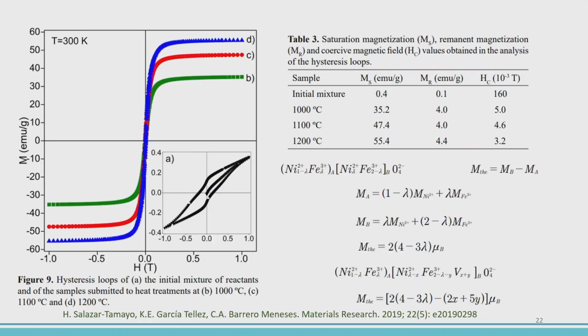And finally, I want to show this, my hysteresis loops of the initial reactants and for the 3 different temperatures. We just want to concentrate on the saturation magnetization, and you notice that as the temperature increases, the magnetization increases. How to explain this? I saw earlier work yesterday that perhaps there is a canting, and with this formula we are not assuming canting, we are assuming that this is a collinear ferrimagnet.